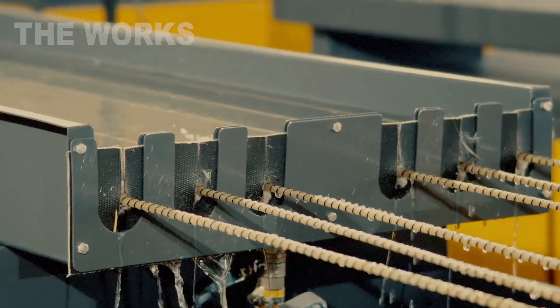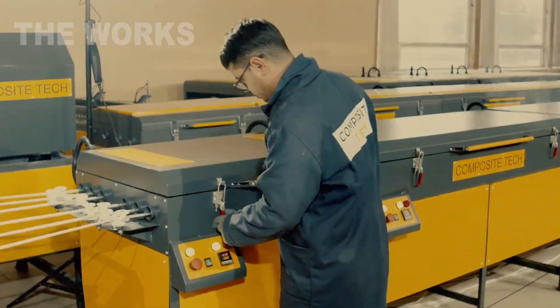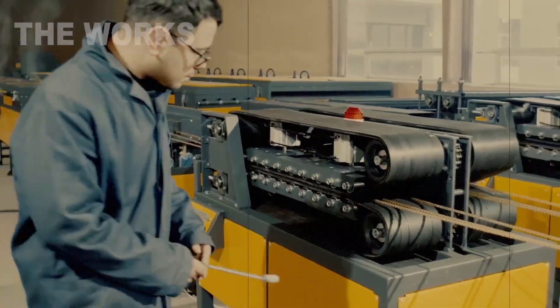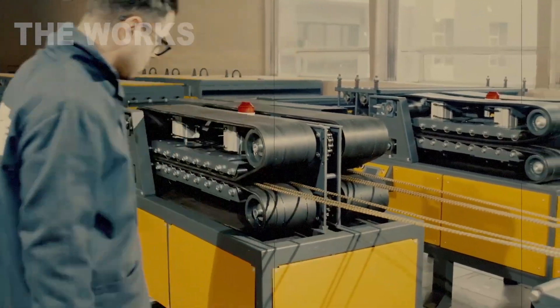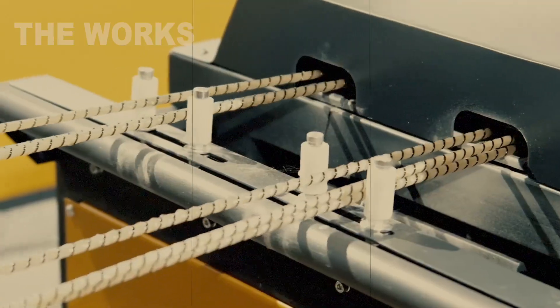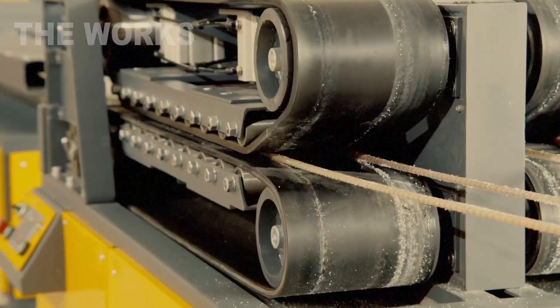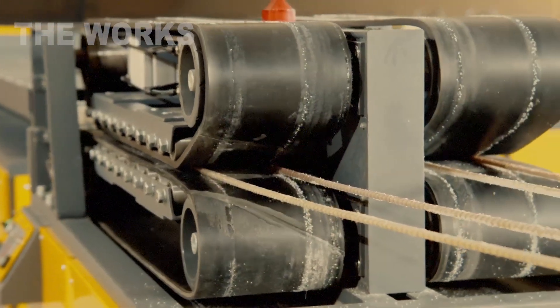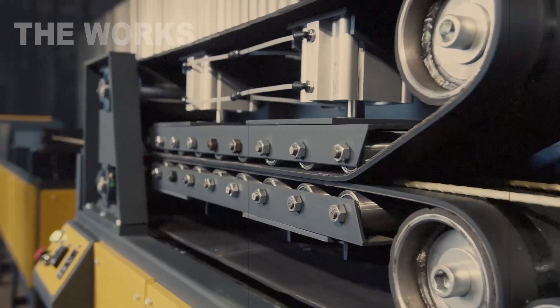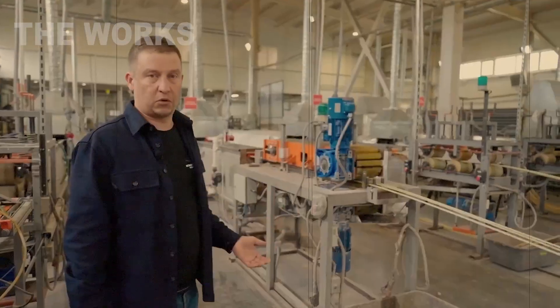But what is pulling it through this long journey? At the end of the line sits a special pulling device — typically two caterpillar track mechanisms, like those on a tank, positioned one above the other. They gently but very firmly grip the finished solid rebar and pull it at a constant, precisely controlled speed. It is this machine that provides the force to draw the glass fibers through the resin bath, the forming die, and the oven. The speed of this movement is one of the most critical parameters controlling the quality of the final product.